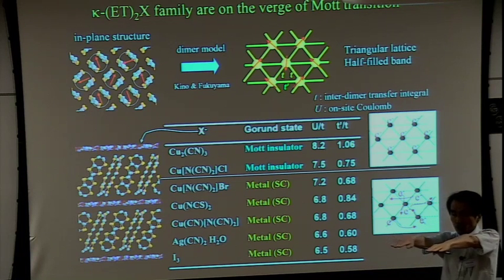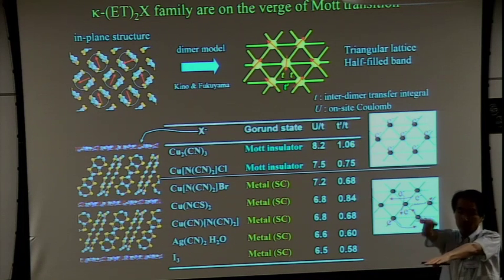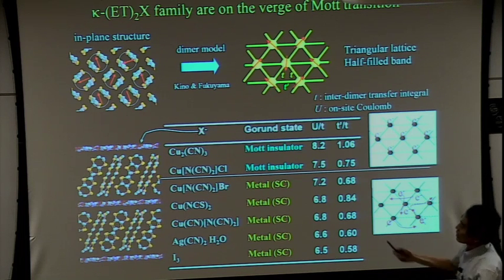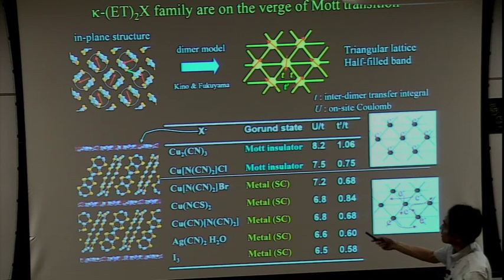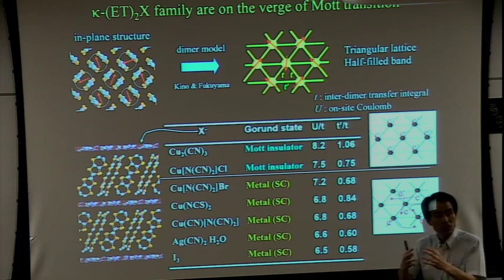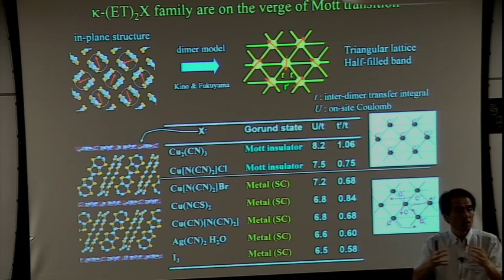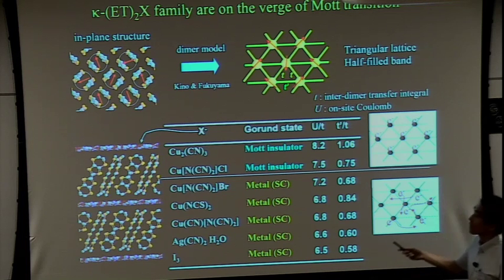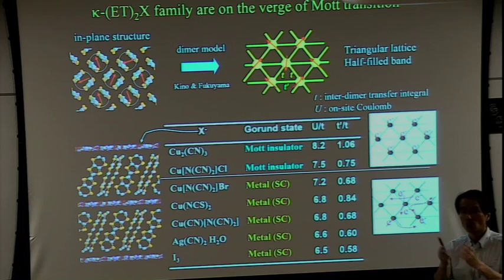So even if the molecule approaches in these in-plane directions, the overlapping is very small. But in the perpendicular direction, the overlapping is very effective. So this dimer has very strong hybridization between the constituent two molecular orbitals, the HOMO orbitals.